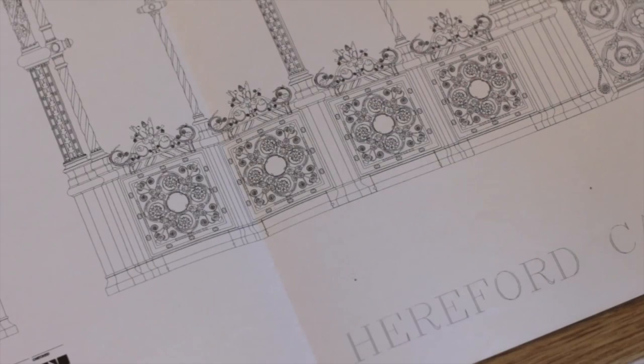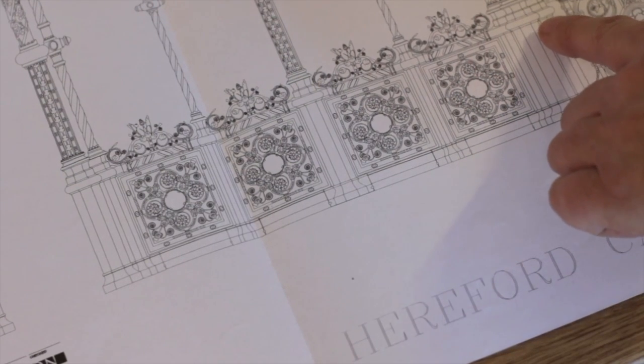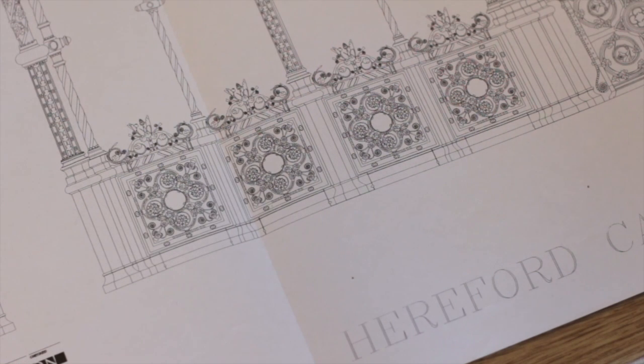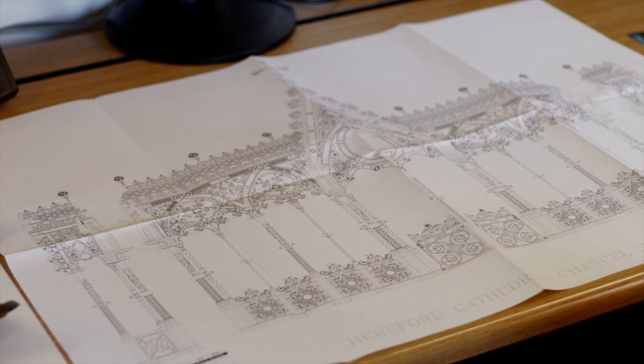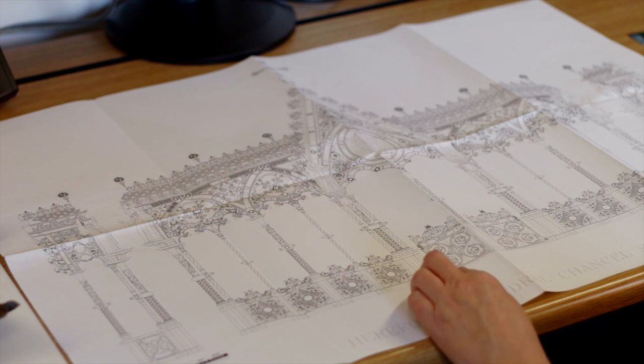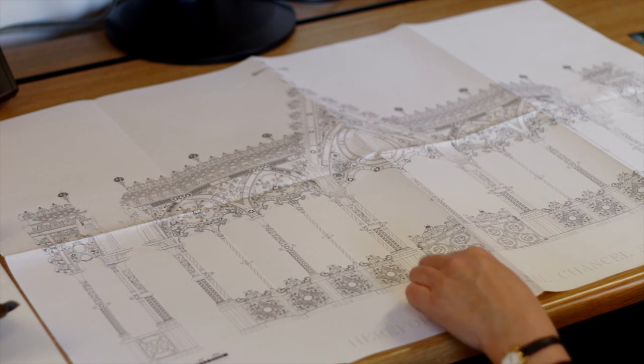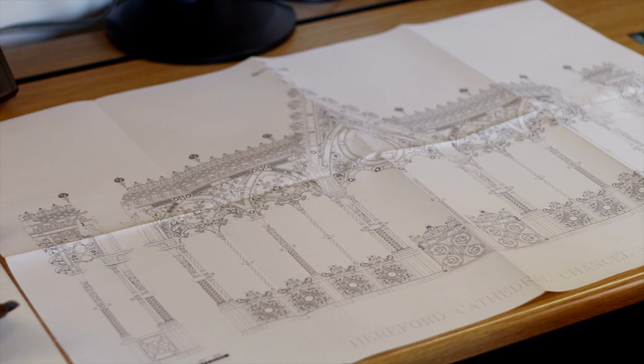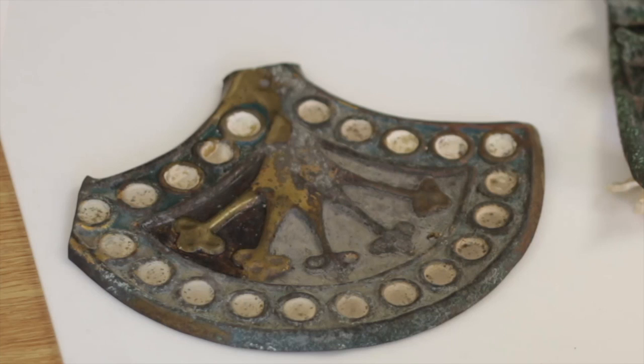Another important point was the base columns, the cast iron columns, which supported the weight. The screen was originally intended to be freestanding, but the V&A realised that it needed to make it absolutely secure in terms of structural stability. So the first process carried out was ultrasound scanning of the cast iron columns to check for any cracks or defects. There were surprisingly few defects and imperfections. A few repairs were carried out ultimately, but then all the columns were reinforced with steel rods internally, which were bedded into the plinth, which was ultimately designed for its display.